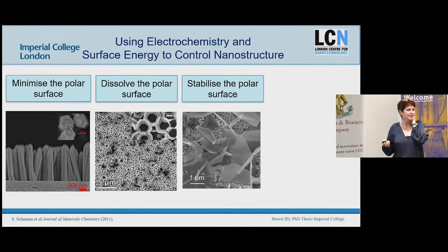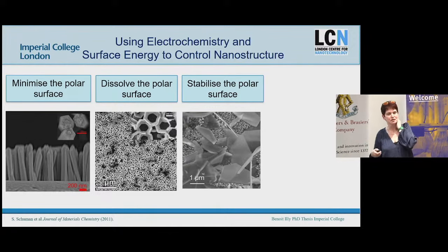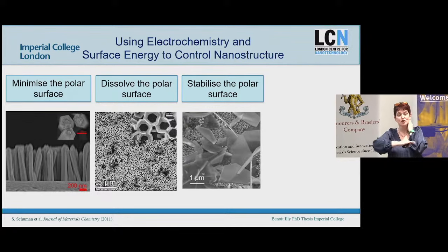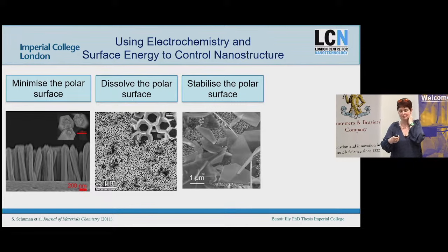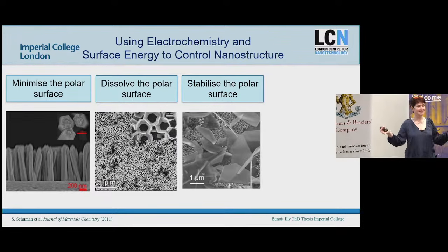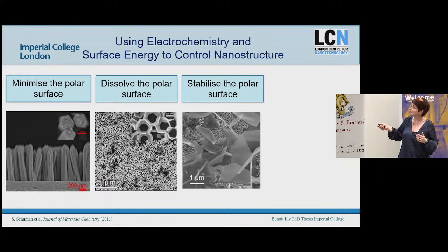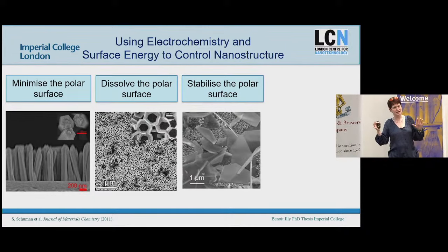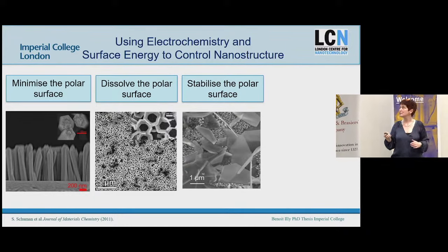You can then, it turns out, stabilize the polar surface. So if you add something into your solution, like excess chloride, it will neutralize the surface charge. And then the system likes that surface. So instead of the rods, you actually get these giant hexagons with virtually no sides. So you can basically change completely the dynamics of what's happening by playing with the surface energy.